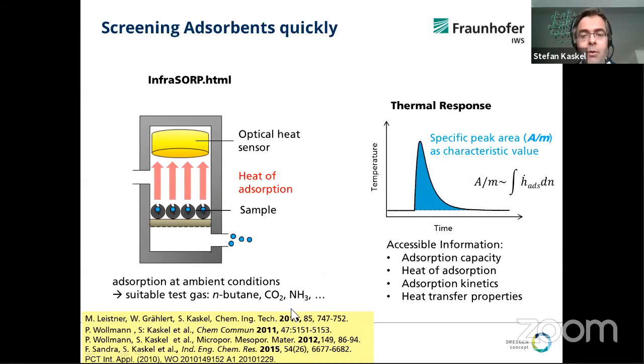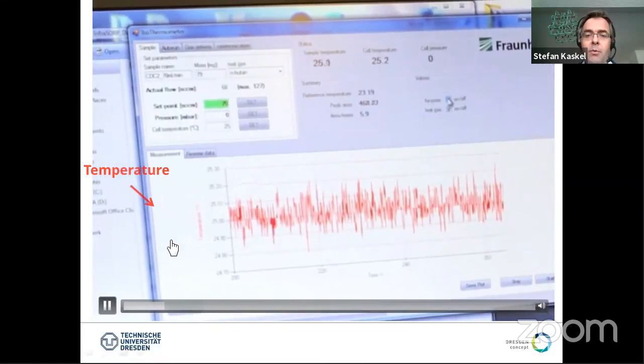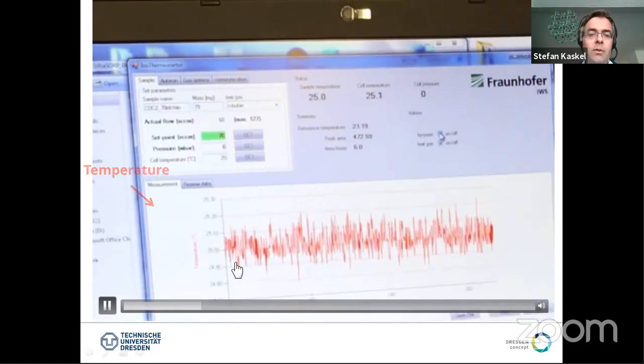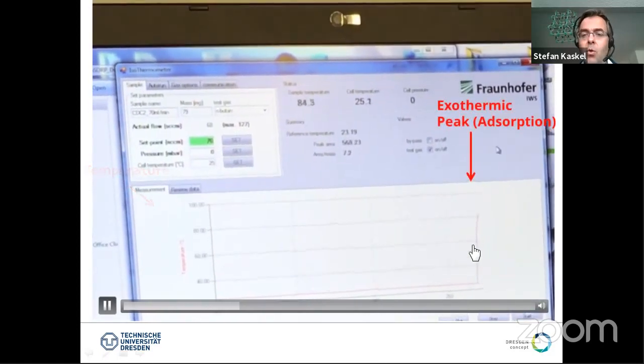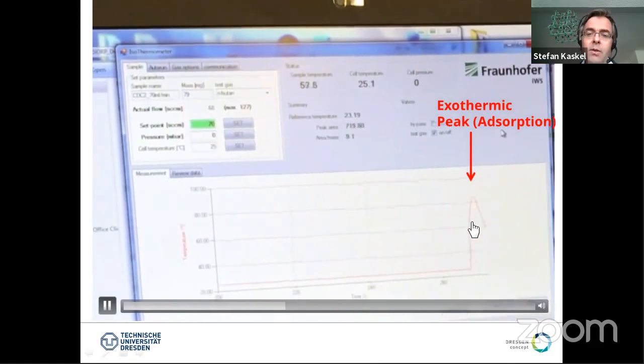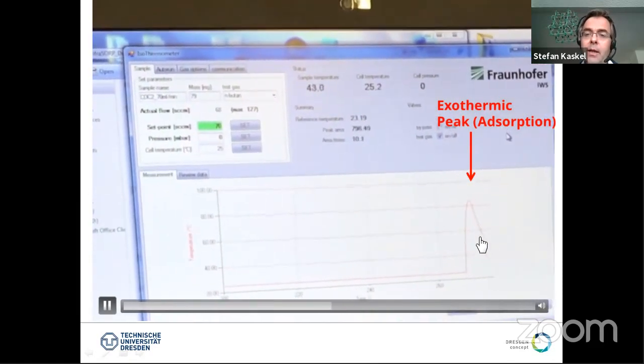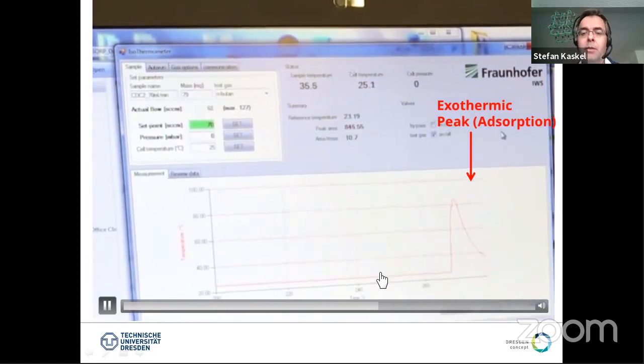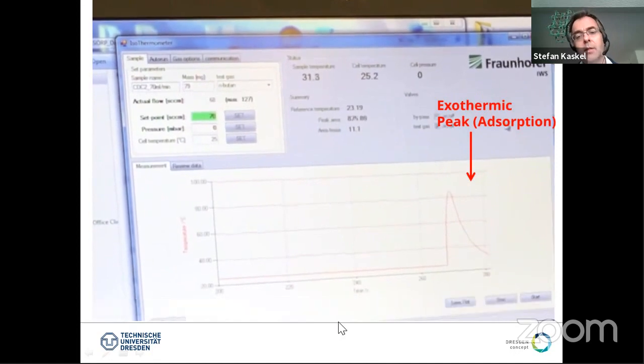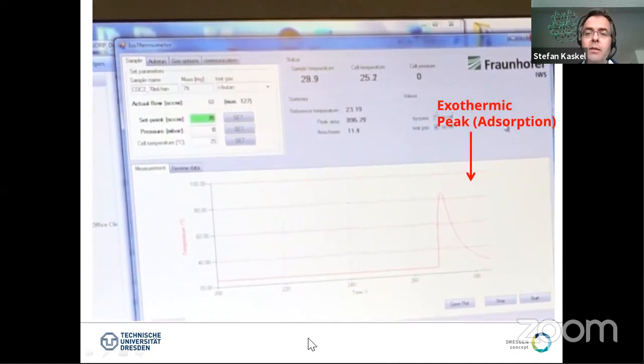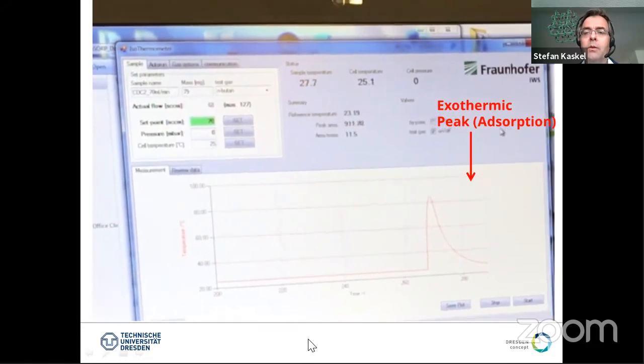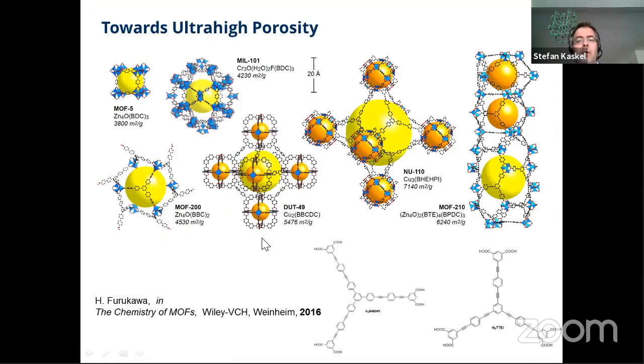You can also use this for chemisorption to identify chemisorption sites, ammonia or CO2 adsorption for ultra micropores. So it's a quite versatile technique. And to give you an example, this was a test measurement for a test user. Here you see the temperature is quite stable. And once the material adsorbs the gas, the temperature rises on the surface to 60 or 80 degrees centigrade. And then basically this was a real life measurement, how you can detect the adsorption with this type of device. So having this in hand, it is possible to discover a lot of new materials and to screen them for a specific surface area and high pore volume adsorption capacity.